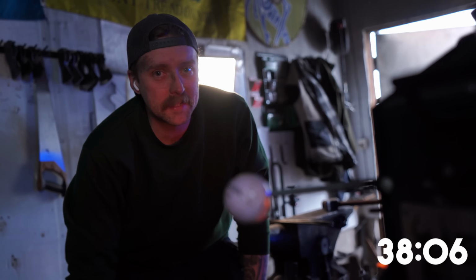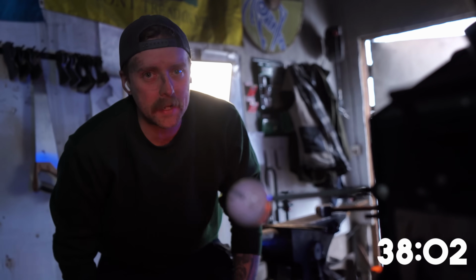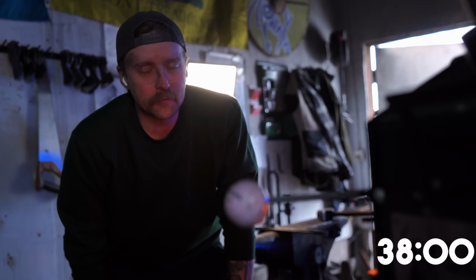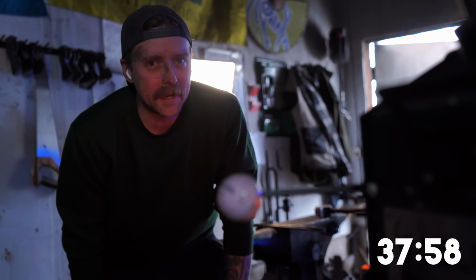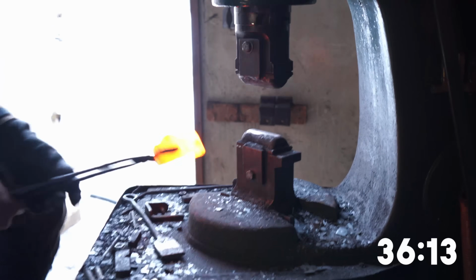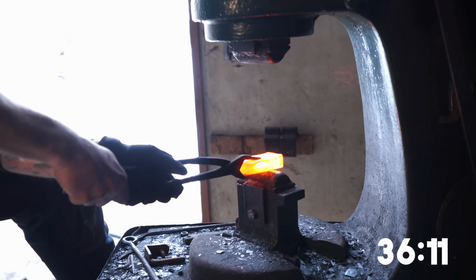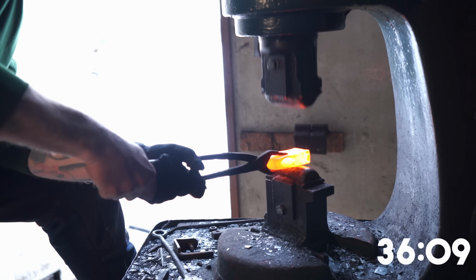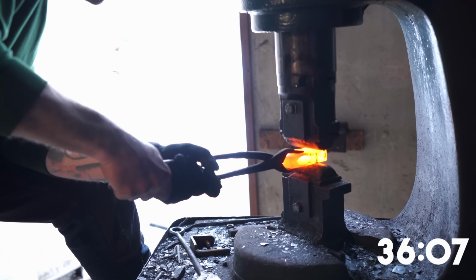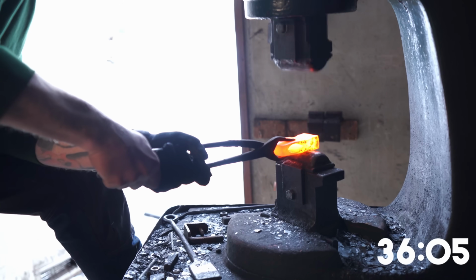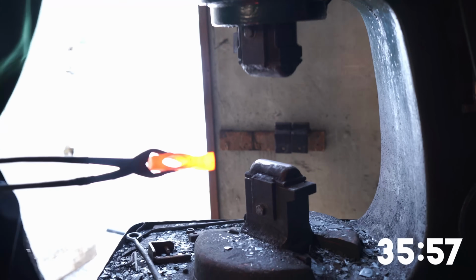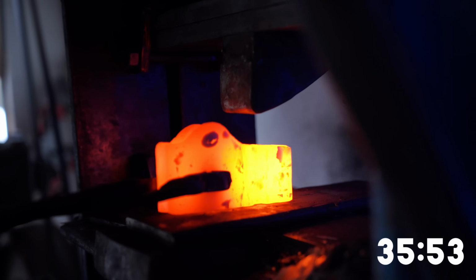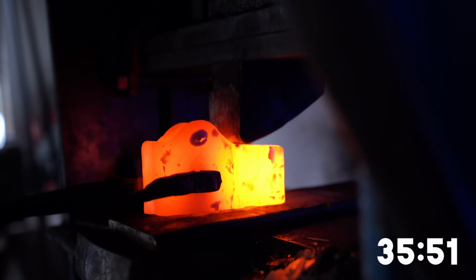It's 38 minutes left and I have to flip it now and start working on the blade, so it takes a little while for that to heat up and it's freaking me out a little bit, I'm not gonna lie. Time is running out quicker than I expected, and once the front of the axe is hot enough I move over to the power hammer. Not to draw out the blade just yet, but to start working on the transition from the eye to the blade. First by thinning it out under the hammer and then by forging in a set down on the forge press.